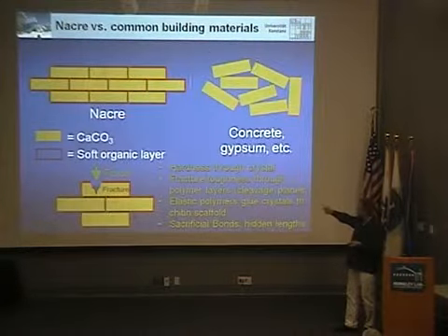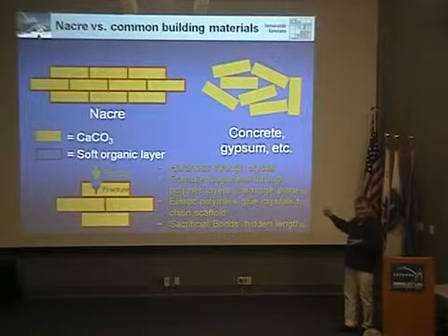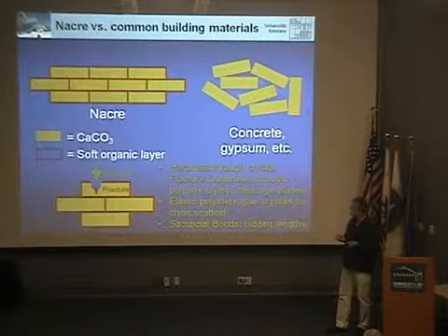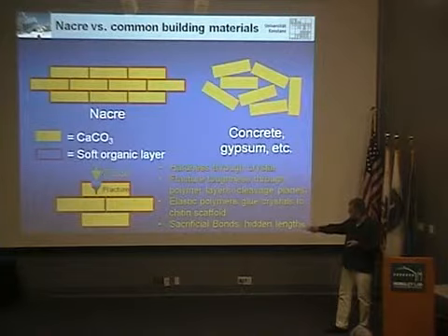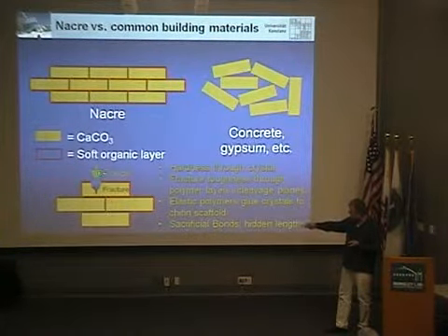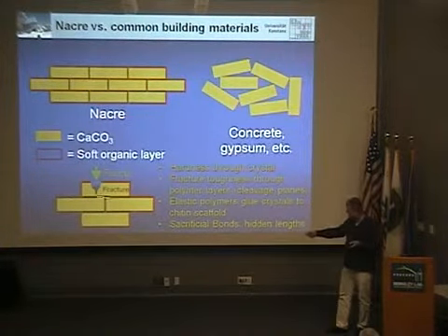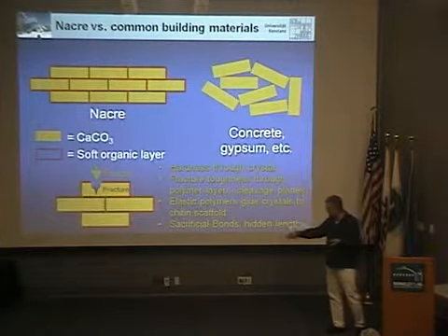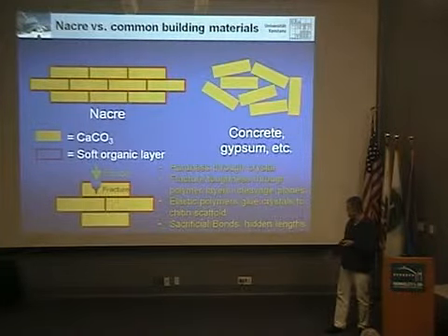And if you compare that to man-made buildings, concrete or gypsum, this is a messy architecture. And that's why concrete and all these building materials are not so strong and tough as nacre, because they are not organized. So if you look at nacre when exerting a force, then you will certainly break the first inorganic tablets, which adds strength to the material. And then you come to the first organic layer, which you have to tear apart, that dissipates energy, and so forth. So you also prevent cleavage planes, which you have in a single crystal.